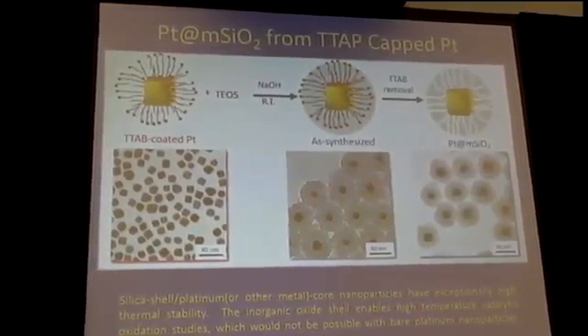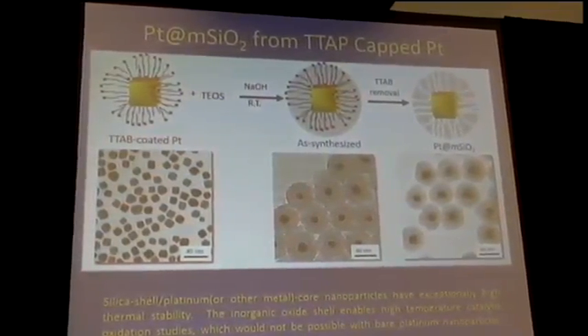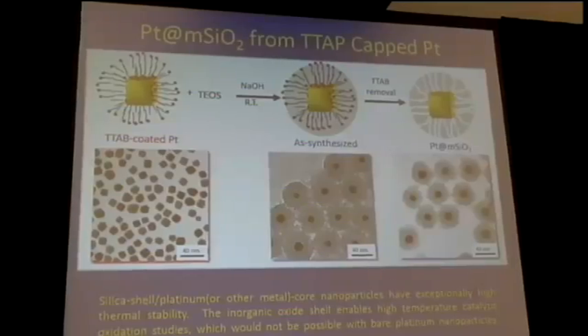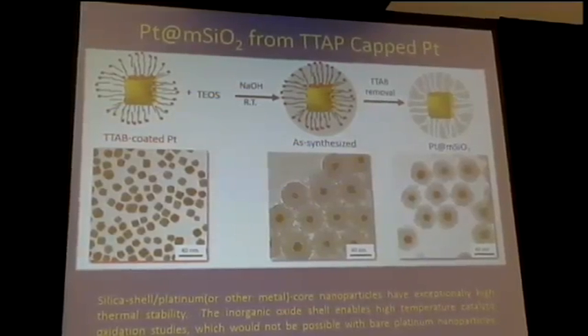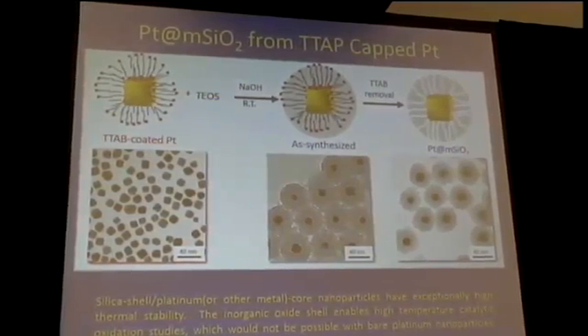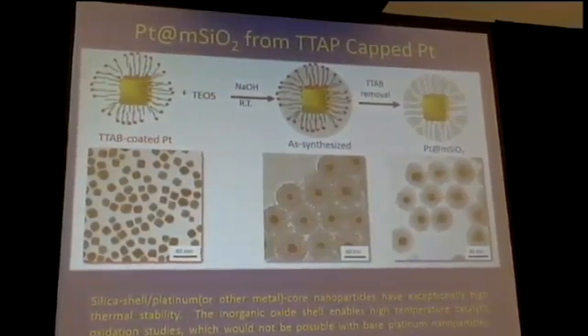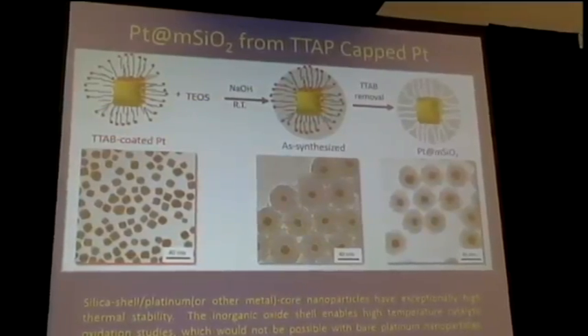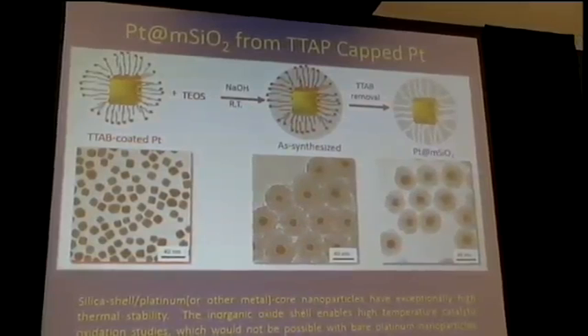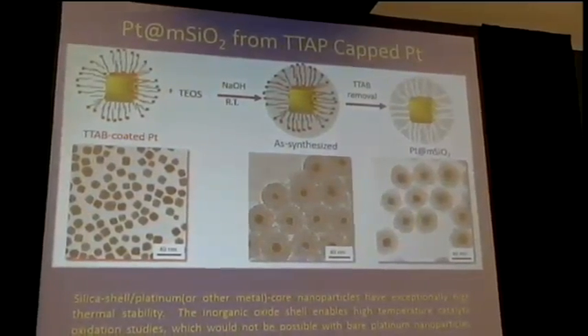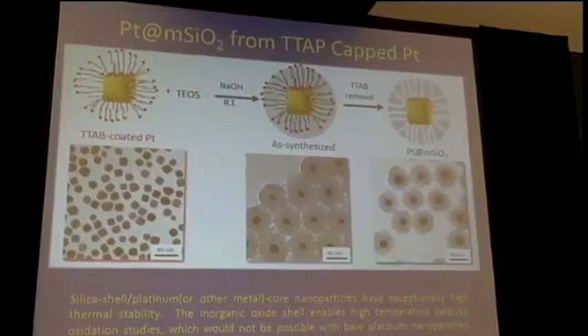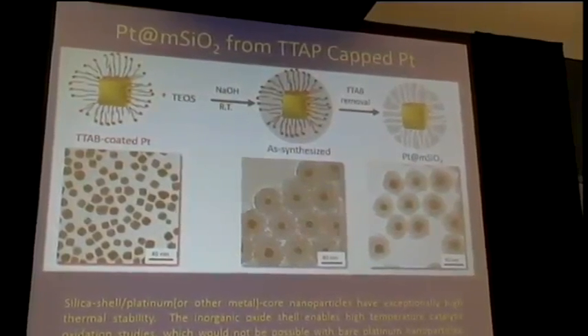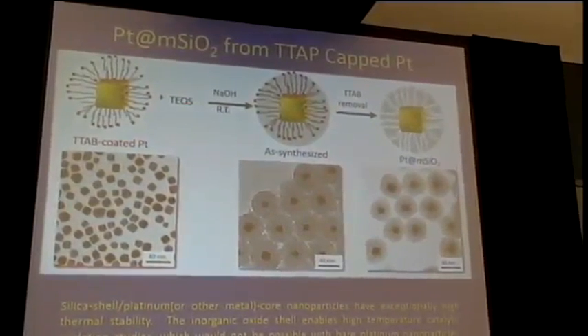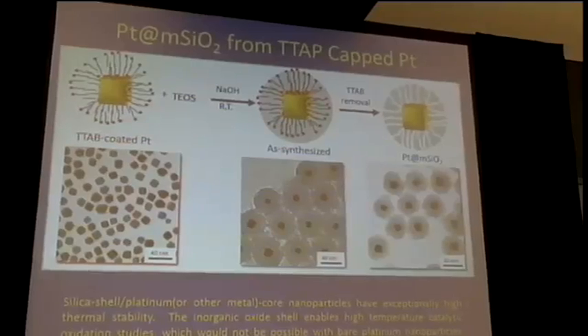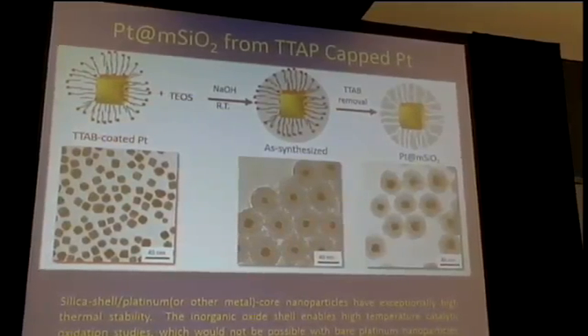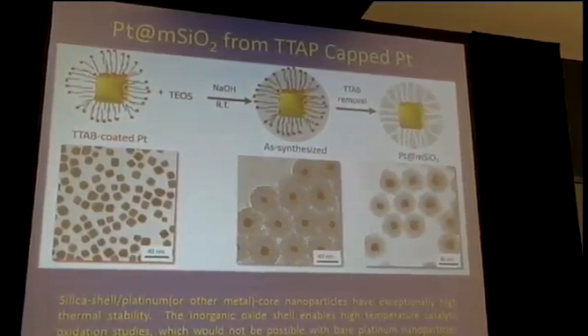Now, the other way of making very interesting structures is the core shell structures, where you have a metal core and then you put a silica shell which is mesoporous in there. And these structures are very important if you want to do high temperature catalysis. The metals of the size that you desire, sometimes 5 nanometer or 3 nanometer size, have a much lower melting point than the bulk materials. So if you go to high temperatures, platinum or gold or any transition metal melts at a lower temperature than the single crystal, okay? Hundreds of degrees lower.